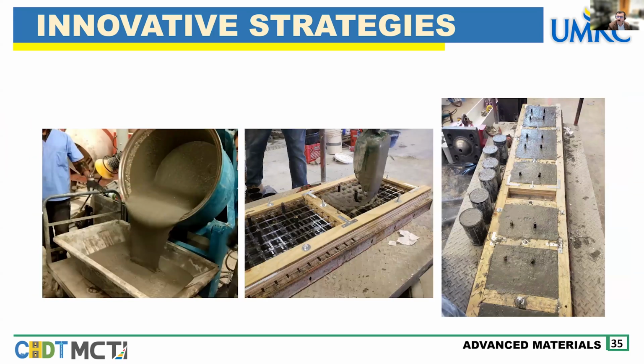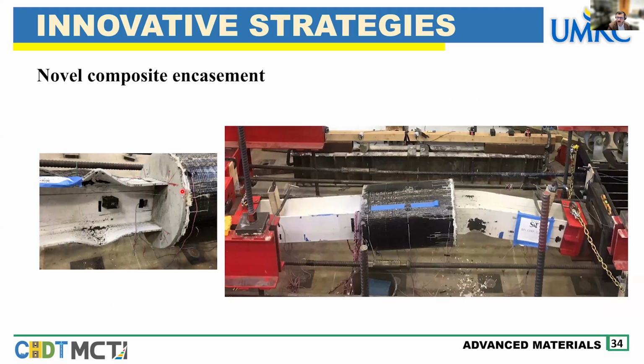And sorry, as you can see here, this is a more close-up picture. This is the steel H pile, and this is the corroded region of the steel H pile, encased with this jacketing of CFRP, carbon fiber reinforced polymer, and also the concrete fill. And we were able to move the local buckling, as you can see here, outside this repaired region, which shows us the repair